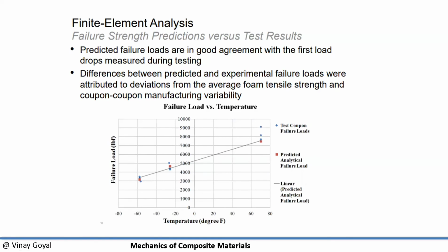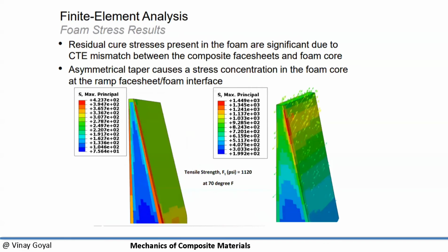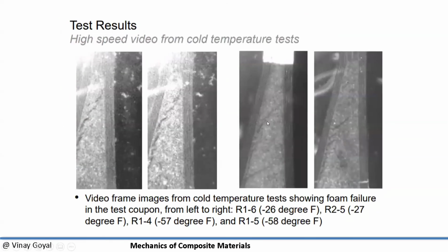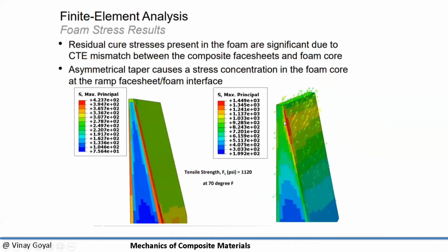And so you want to really look at the whole spectrum. The analysis anchored at this point may not have been as good at predicting failure here. So you have to make sure the failure analysis models work well across the whole temperature range. That's very important before you can start translating these models for other applications. But once the physics of the problem were well understood, it was much easier then to start predicting what could happen here. And again, you can see how this max principal stress is aligned with and is perpendicular to these cracks that develop within the foam, which tells you that the max principal stress is a good predictor of failure.